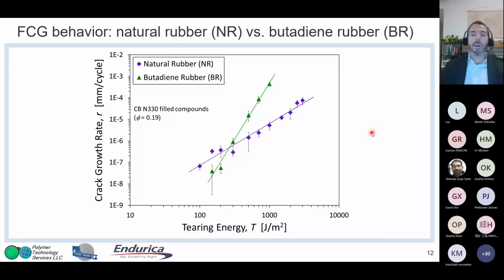And here's some examples of natural rubber and butadiene rubber, basically formulated the same way in a carbon black filled formulation at pretty normal filler volume fraction that you would see in tire and automotive rubber parts. And what you'll see is, and keep in mind this is crack growth rate, so lower is better. It's not so clean to say that natural rubber is better than butadiene rubber. It really depends. At low severities, actually butadiene rubber has slower crack growth than natural rubber, and at the high severity end, there's a flip, and so there's a crossover.